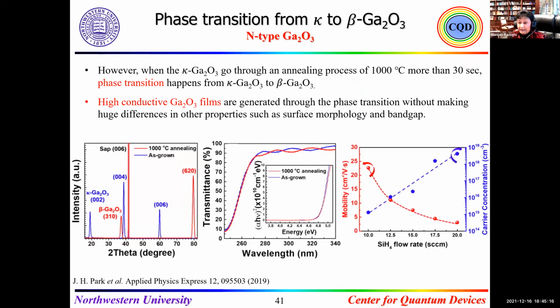But after that, something important happened, because we learned from our experience with aluminum nitride. Everything we saw in the characterization - we were doping at the same time with silicon, but the material we had was resistive. It was impossible to get any electrical results. So I said, all right, let's do the annealing.